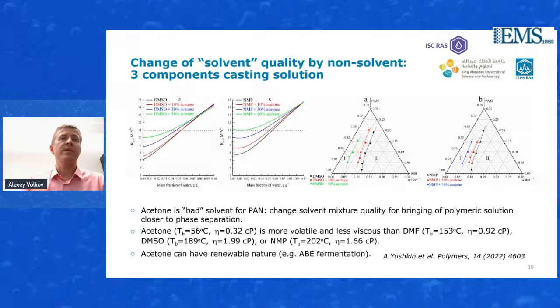And the good thing is that acetone can also be produced by fermentation. It means that we can replace the classical solvent by a renewable solvent like acetone. And that's the same as what we showed on the previous slide. The phase diagram also shows that when we add acetone, we drive the system closer to the phase separation. So it means that we need less water to get the phase inversion with the forming of the